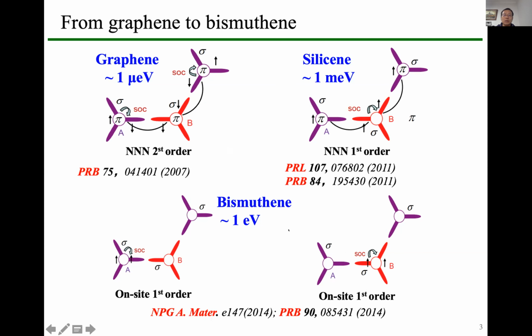Along this direction, if we use an even heavier atom, such as bismuth, then we can construct bismuthene, which also has a similar honeycomb lattice. So in this case, the band gap is about 1 eV. So this means this material might be possible to host a quantum spin Hall edge state at room temperature.